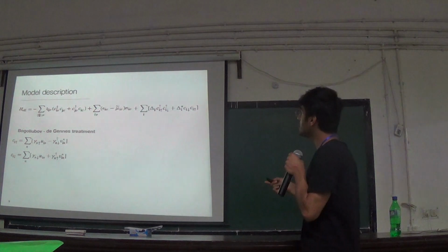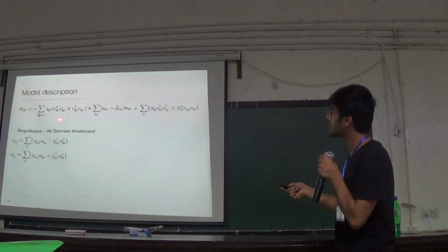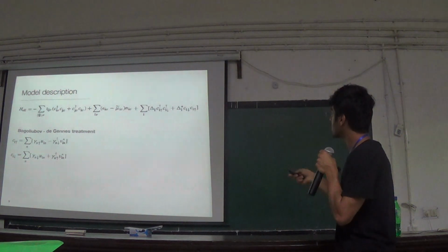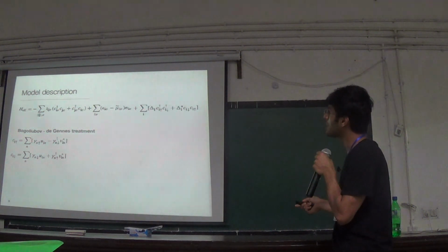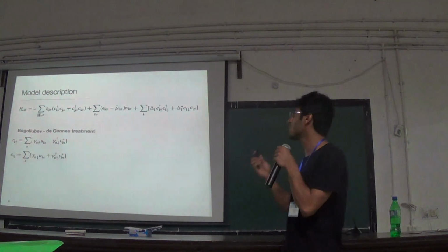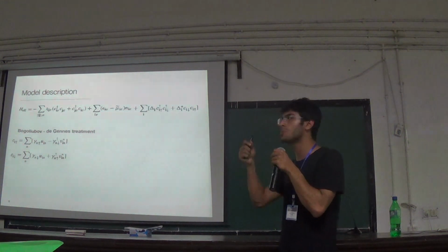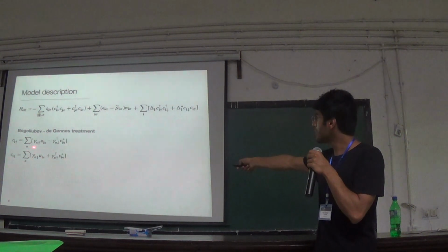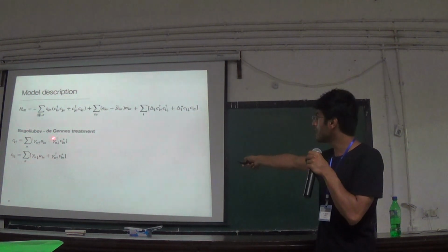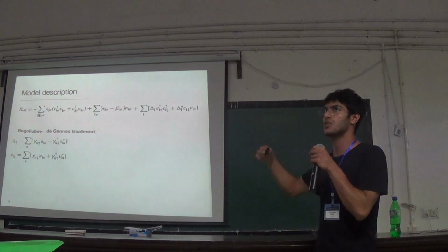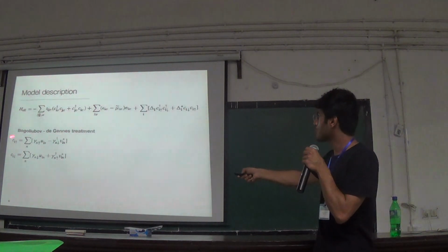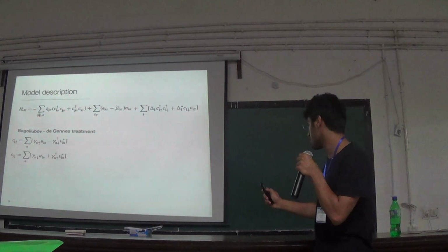Initially we know that the system was diagonalized in the C operators, that means the electronic operators. But now, since there are some cross terms, the usual way to diagonalize this is to think of the quasi-particles being a superposition of a hole and an electron. Now these gamma nu operators define the operators for excitations, for a new type of quasi-particle in the system. And they are the superposition. You can invert them and you will see that they are the superposition of these C and C dagger operators.